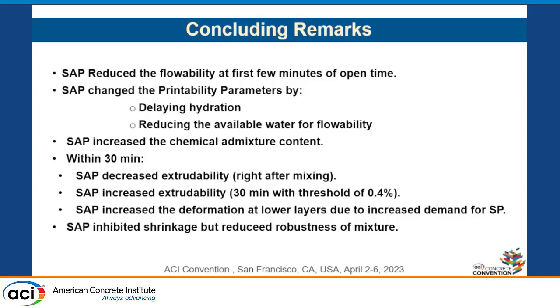And SAP increased the chemical admixture content. I don't like it, not only because of costs. I don't like it because during the open time, SAP can manipulate the viscosity and the rheological properties of my mixture, and I don't like it. So there's something I have to work on to see how I can produce a more robust mixture. And SAP decreased extrudability right after mixing, but increased extrudability within that open time.